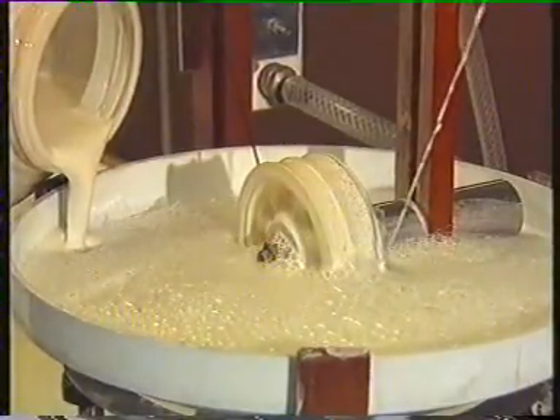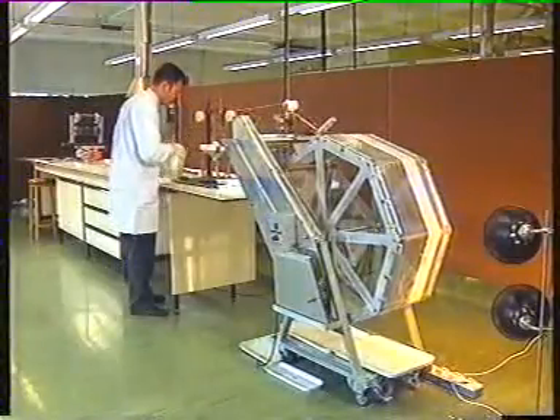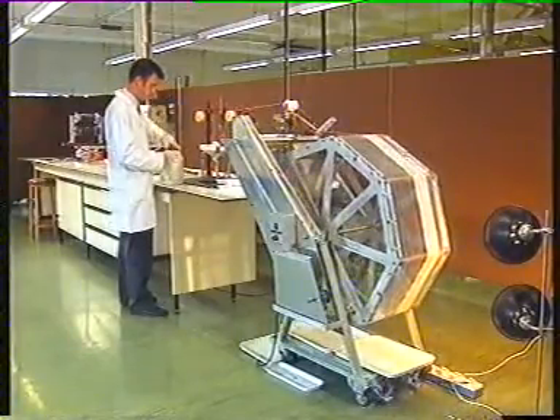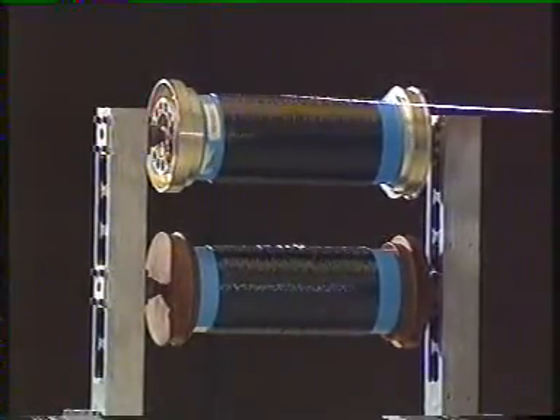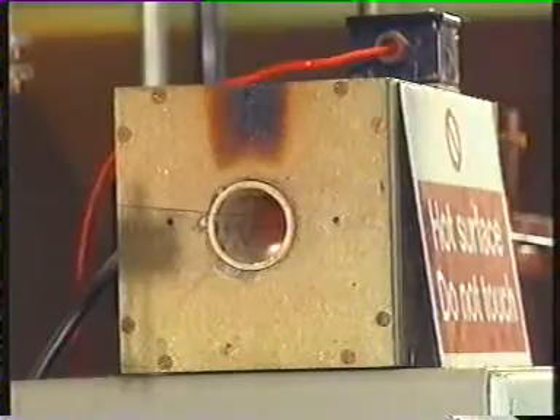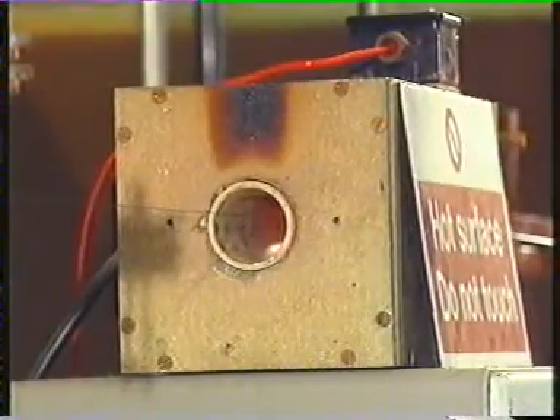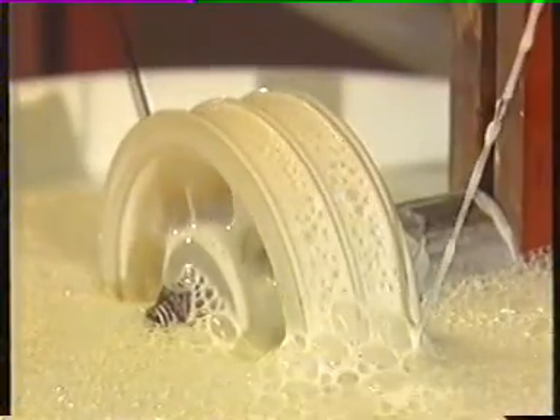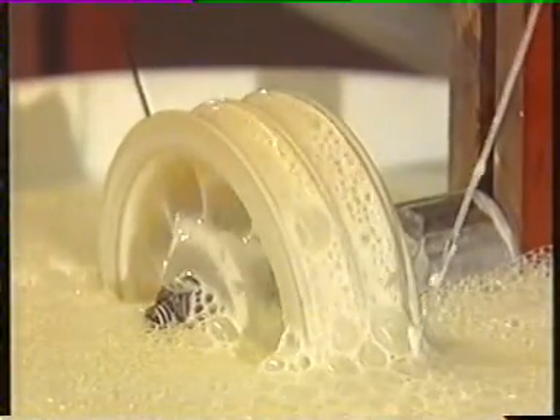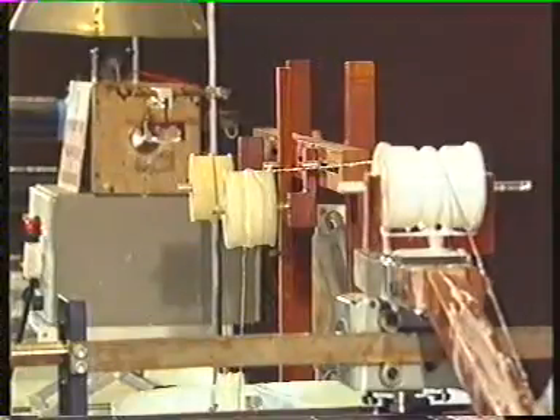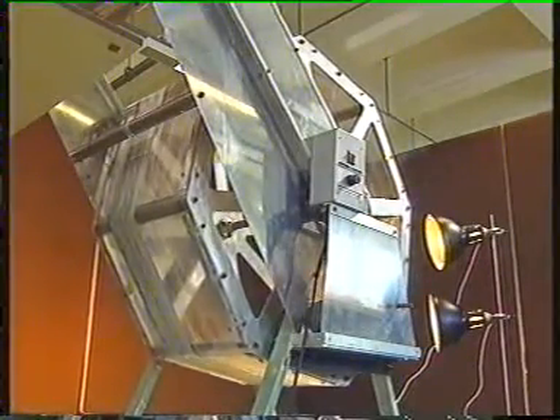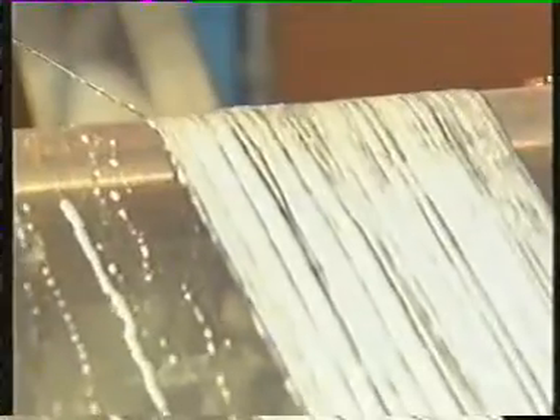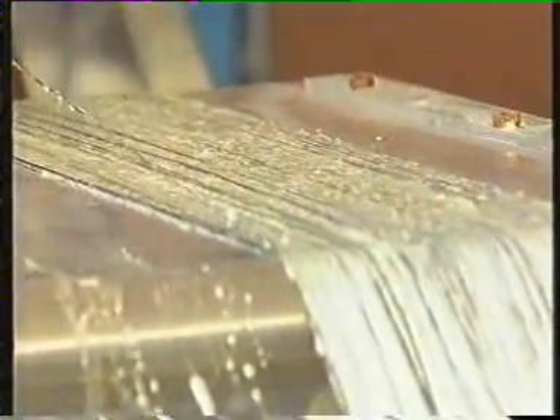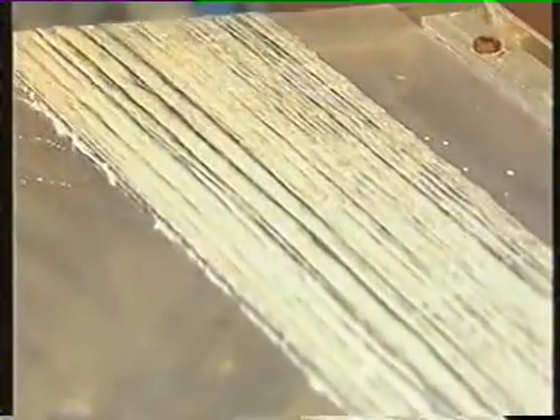Composite ceramics are safe and reliable because of the way they're made. In this prototype production line, they start life as a continuous silicon carbide fibre. After passing through a furnace to burn off their protective coating, the fibres are passed through a slurry containing glass particles and a binder. This will form the matrix, holding the fibres together. The coated fibres are wound onto a drum in bundles of about 500, where they're dried. They're then hot pressed and heat treated in order to give a ceramic matrix composite.